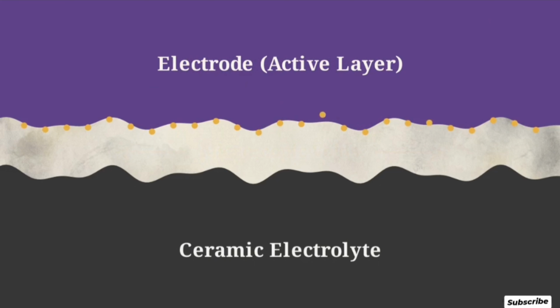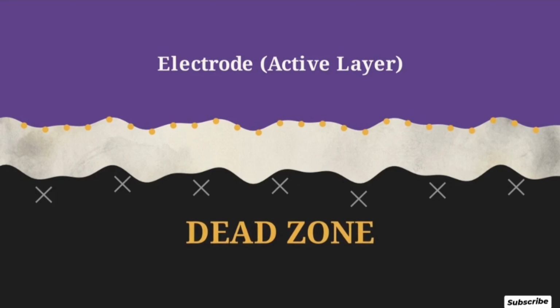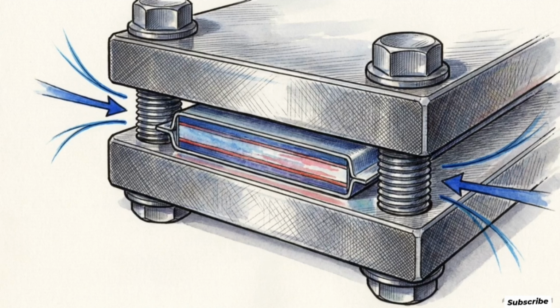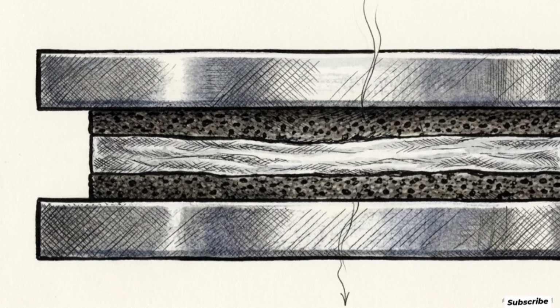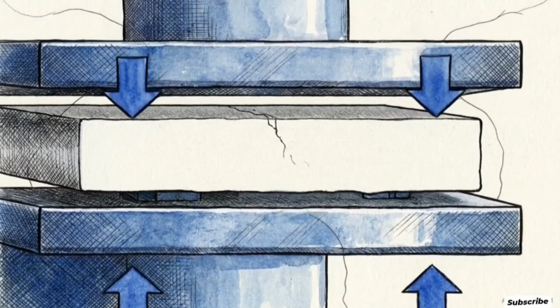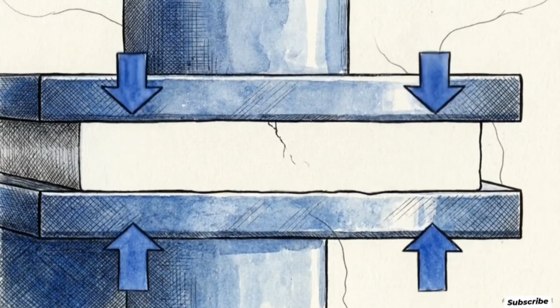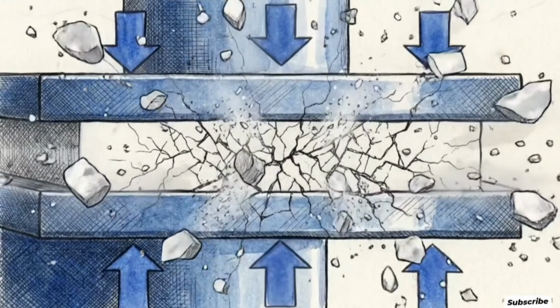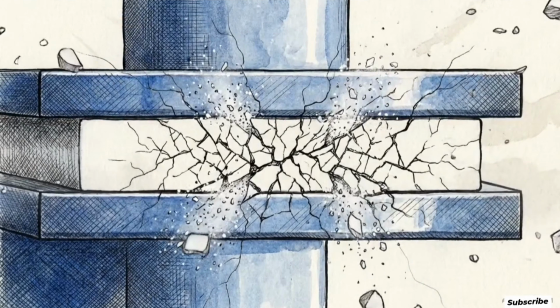This contact loss halts ions. They can't move through empty space, creating dead zones that kill power transfer. Engineers attempt to force these layers back together using stack pressure, an intense external force applied to crush the battery layers into constant contact. But ceramics are brittle. Constant volume changes and crushing pressure eventually cause the electrolyte to shatter, forming deep microcracks.